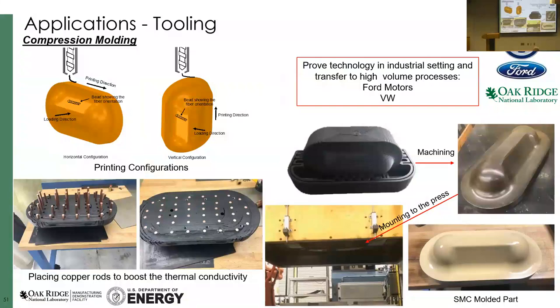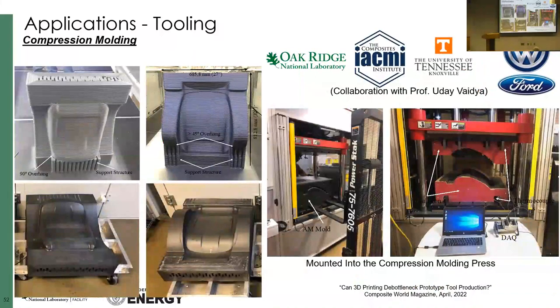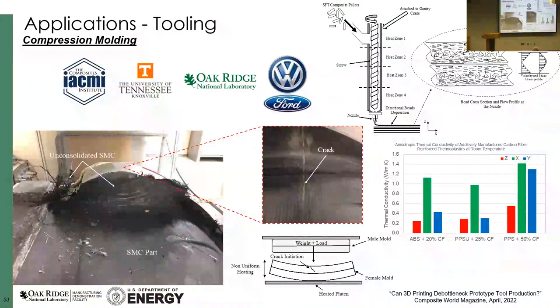But here is the thing, compression molding, you are not putting it in an autoclave where everything is good by convection, it's heating up. You're heating by conduction from the backside. And you have a big block of polymer, which, you know, the thermal conductivity of the polymer is great. Great is, being sarcastic, by the way, right? So just in case you didn't catch the notion. It's bad. Thermal conductivity is so bad. So if I'm heating just by conduction, I said okay, let's put, I was so desperate, let's just put an insulation box. Maybe I will get there at the temperature, right? And then you put a deck and everything, and I said you keep waiting next to it for about 3 hours, and then you fail, right?